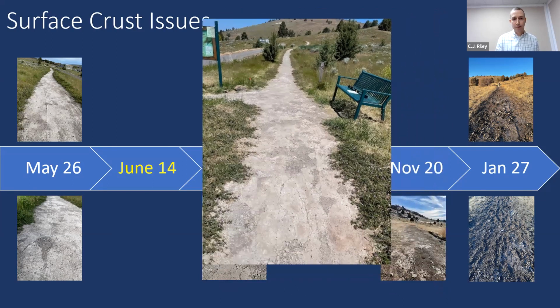If we move into June, we did have quite a bit of moisture in our spring this year. So there was some additional wetting, maybe some additional moisture helping us bind material. But we did start to see lots of use. We didn't close the trail and it wasn't allowed to cure in any meaningful way. So people were active on the trail right after the implementation. And you can see how some of this is breaking down. This photo is right at the start of the trail, and you'll recognize that bench there in another photo.